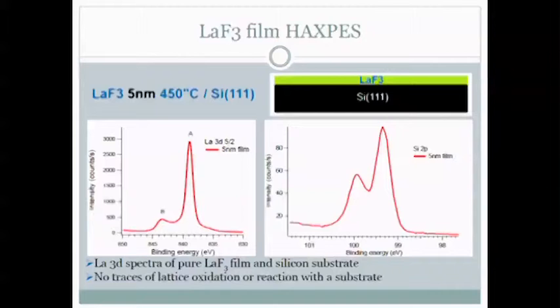Here is the 3d peak of lanthanum fluoride, which has some special characteristic peak, which points us to a clean film. So during the evaporation, we prepared really clean films with no traces of oxygen on lanthanum fluoride, on silicon substrate, and also no chemical reaction between these lanthanum fluoride films and the substrate.